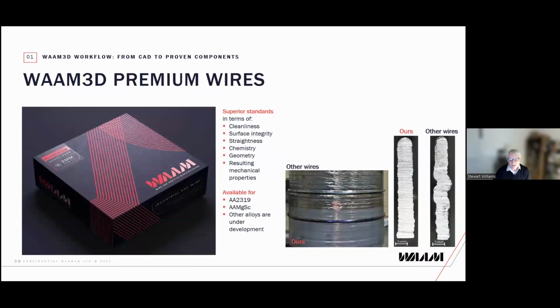So we also had to develop a very specialized wire that has much higher quality than standard welding wire. So you can see actually this is building a part, and we go from our very nice wire to another wire. You can see the change in geometry. Similarly, you can see the change in build quality, and these wires nominally fit the specification, but actually the one on the right is not suitable for AM.